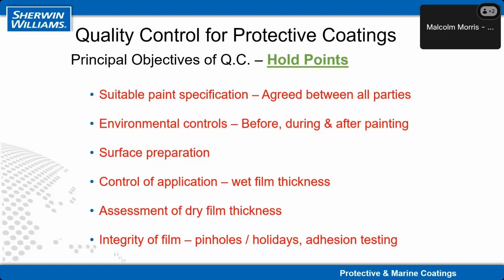Even if you put too much paint on, more isn't necessarily better, because too thick a paint system could actually start to crack and fall off because of internal stresses. So getting the film thickness right is very, very difficult to do, and paint sprayers are an extremely skilled trade to do a good job, but the quality control and monitoring of that is very important. Also the integrity of the film in terms of pinholes, holidays, adhesion testing. All these different factors, different stages of the painting process are crucial and have to be undertaken by trained personnel. And training is the absolute mantra.